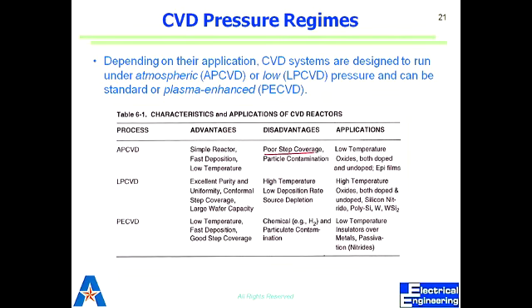Okay, this should have been before, because atmospheric pressure CVD, LPCVD, and PECVD all have different pressures and different temperatures. We have seen these numbers: LPCVD has high temperature, and PECVD has low temperature, and atmospheric CVD is a simple reactor which is at atmospheric pressure. In all those cases, we have different advantages and disadvantages. LPCVD gives us excellent purity and uniformity, and very conformal step coverage. What is the only issue with LPCVD? A major issue? High temperature.